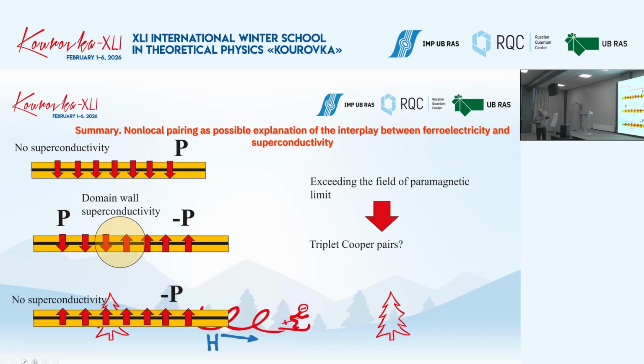Let me summarize. We suggest a sort of non-local pairing, interlayer pairing, as a possible explanation of the experimentally observed interplay between ferroelectric and superconducting orders. What we can explain is that if we have a homogeneous dipole moment in our sample, we can have zero superconductivity, and all superconducting correlations are suppressed. For opposite orientation, again, we do not have superconductivity, but if we have some domain structure, we can have superconducting nuclei localized near the domain walls, and this seems to be in correspondence with experiment.